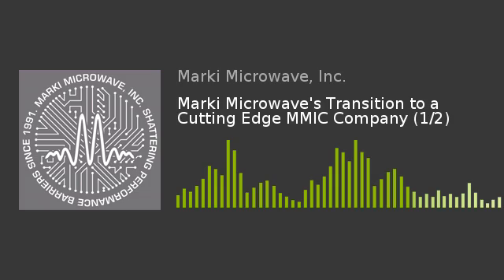Yeah. And this is a subtle technology point that I want to elaborate on a little more, because it's very esoteric and confusing for somebody who comes from outside of the hybrid assembly area. The way that Metelics made their diodes, we need to get JC on it. Yeah, JC's a good interview. Yeah, he's a good guy. So they would make one type of diode that's a beam lead diode, where they would fabricate the junction, plate gold on top of it, and then etch underneath the gold, etching the body of the wafer. Lift off.